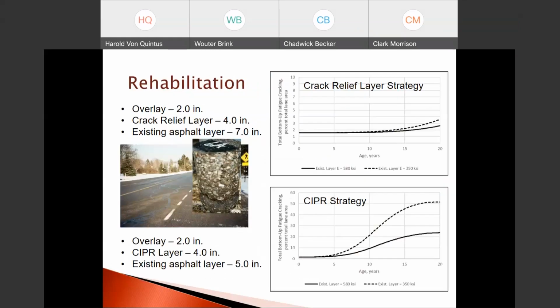This is another example comparing now just the crack relief layer strategy to the cold in place recycling strategy. The short dashed line is the 350,000 PSI of the existing asphalt layer. The solid line in both graphs is the 580,000 PSI. So the condition of the existing pavement can make a big difference. The type of rehabilitation or reflection cracking mitigation strategy can also have a big impact, as shown in these two